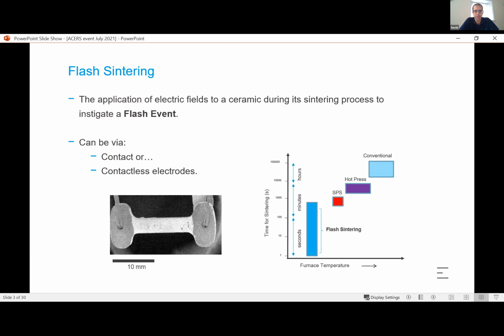So what you're getting is sintering in a matter of seconds, as opposed to a number of hours, and that's generally occurring at furnace temperatures of, say, 700 to 1000 degrees instead of, in the case of zirconia, 1500 degrees. A good example of this is a video of the discovery of the flash event, let's say. It's called flash perhaps because it happens as quick as a flash in the case of the discovery of the thing, but often it optically emits as well. So if I just play this for you, you see this rapid shrinkage and the optical emission there, and that's it sintering very, very rapidly.